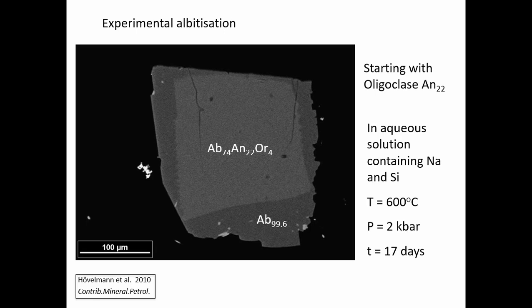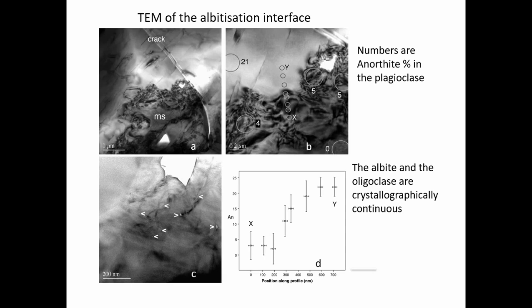Here is a SEM image of the reaction, which maybe you can't see very well. There's a very sharp interface of albite, which is 99.6, virtually almost pure albite, sodium aluminosilicate. In the center is the original material, but that interface is very sharp, which I will show more images of. So the TEM has enabled us to look closely at that interface. The interface is sharp on a chemical scale, but it's wavy. It's not a straight line, but compositionally it's very sharp.